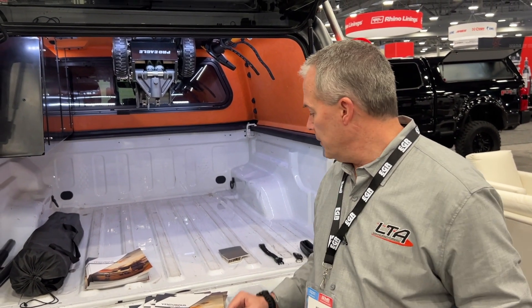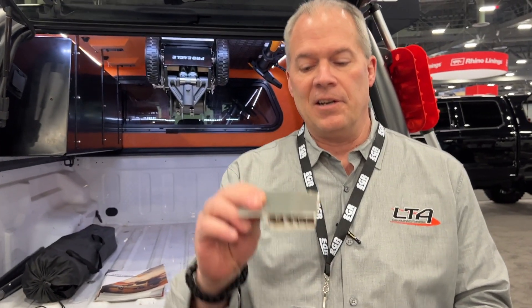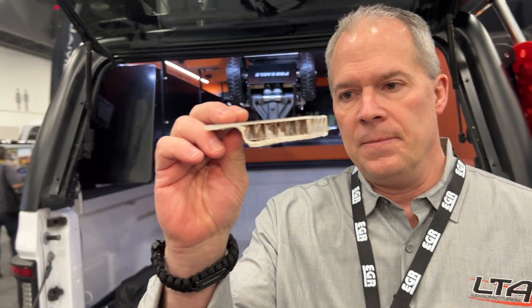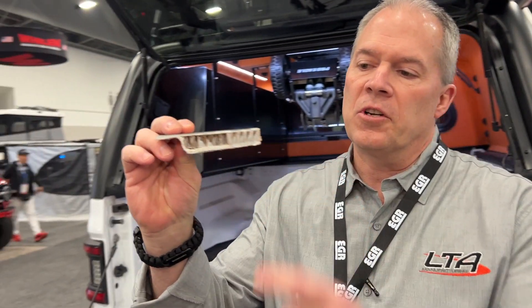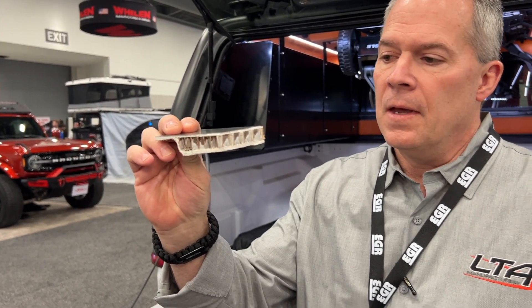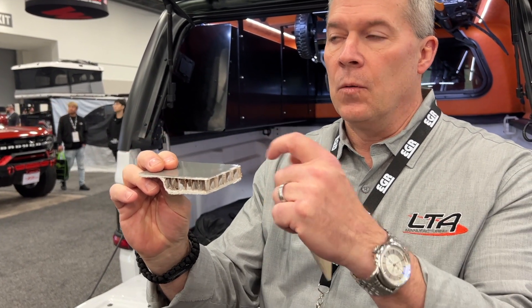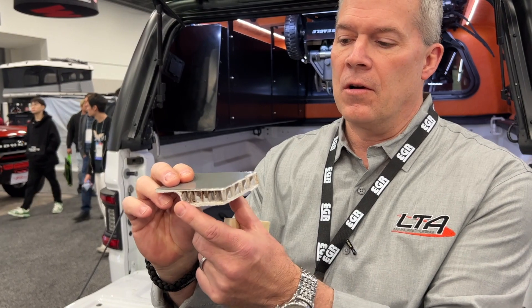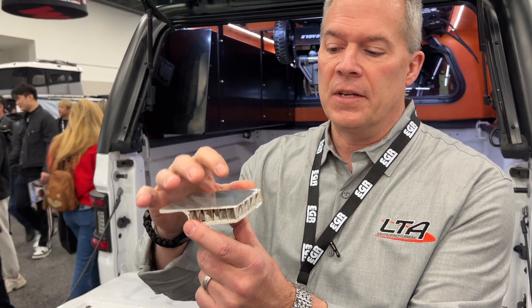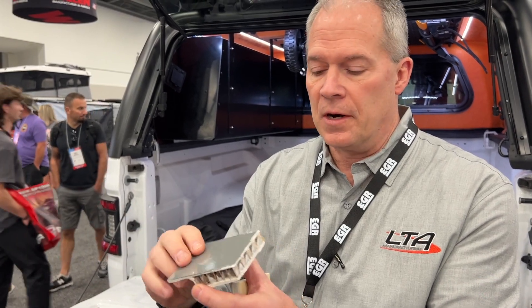This is a sample of a traditional truck top, which is really the way we've been building truck tops for about the last 60 years. You can see inconsistencies in thickness. You can see this reinforcement inside the roof, which is called a honeycomb reinforcement — it's basically a cross-cut cardboard. It works well, although you can't drill through it. Once you try and start mounting all your gear, racks, and tents on top and you drill through this, water can get in, causing rot, delamination, and destroying your truck top.